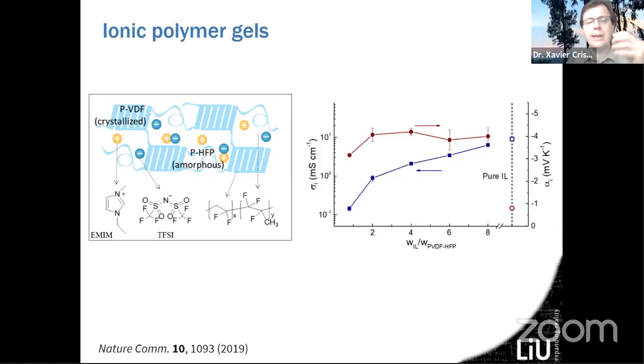So the ionic liquid is just a liquid that you put in, and this liquid is composed of molecular cations and molecular anions, and they really penetrate into this polymer matrix to create a gel. So it's very easy to create, to make, and it appears like a gel.